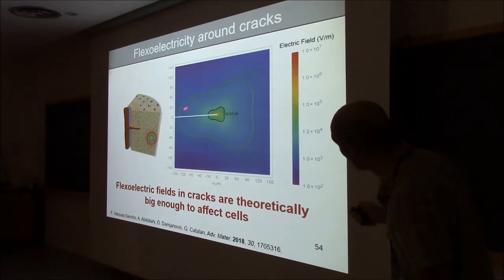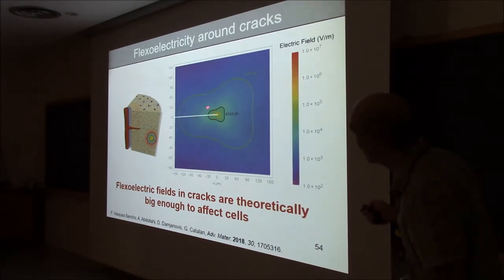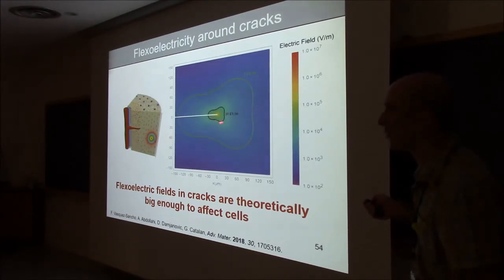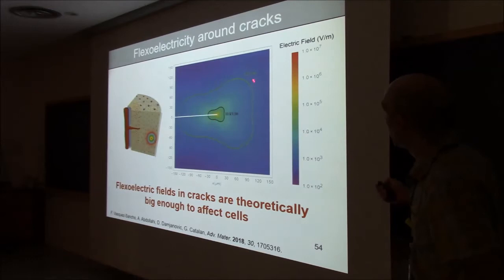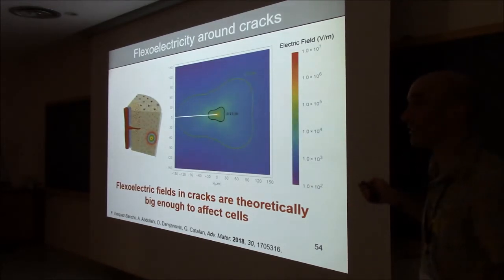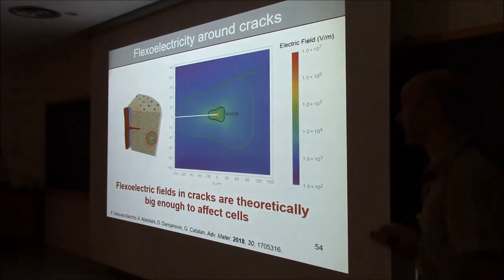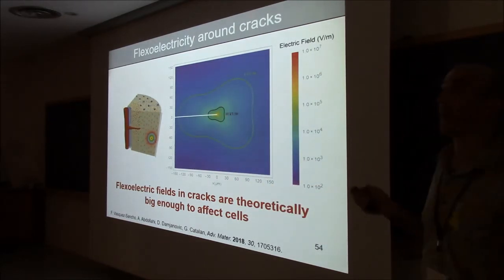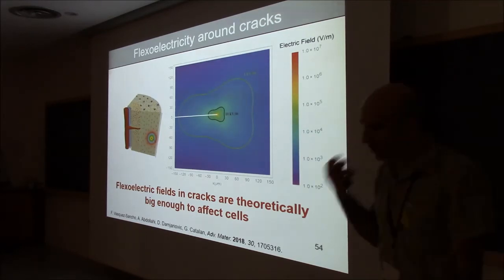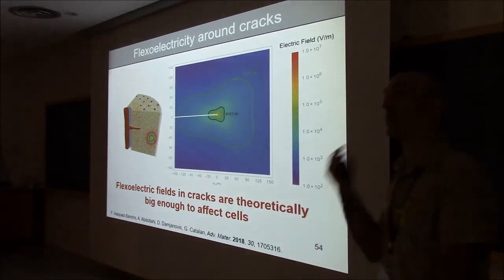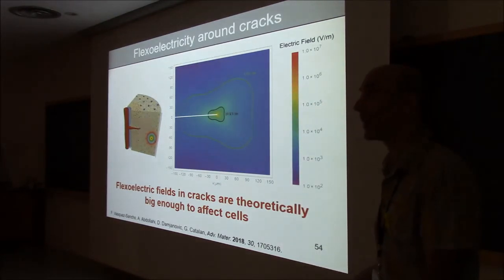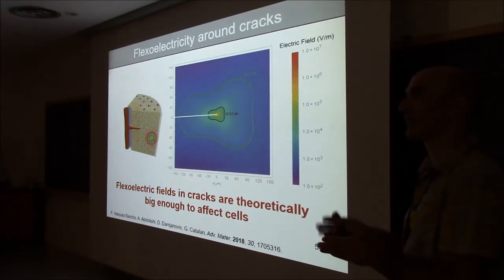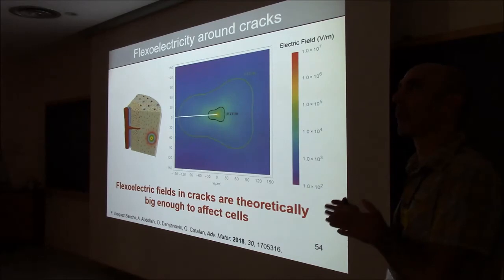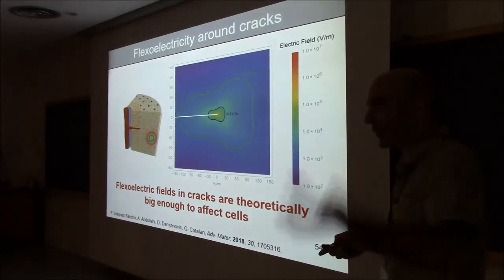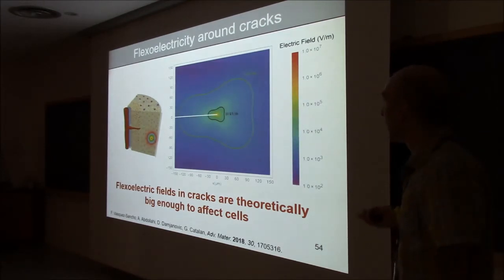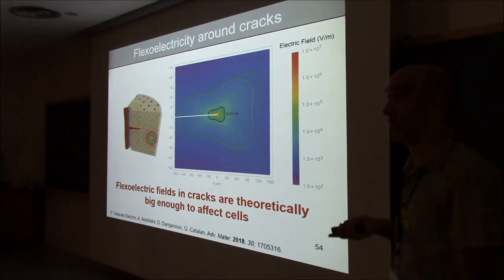Okay? And what I've drawn here, these two contours, are the isocontours of the known electric fields capable of electrocuting directly, electrocuting your sample, your cell, killing it, and the isocontour of the electric field that is known to be able to electrostimulate your bone cells. And these contour fields are the flexoelectric fields around the tip of a crack. So bottom line is, we think that flexoelectricity does play a role in the healing of your bones. It's the way in which your bone, when it has a fracture, tells the repair cells, come here, there's a problem. So besides all the functional curiosities and interesting physics of flexoelectricity, it may well be the case that it plays an important role for us.